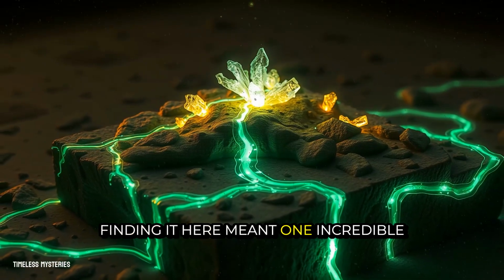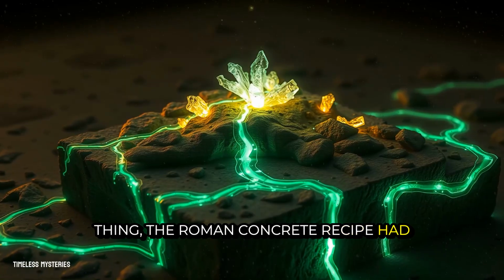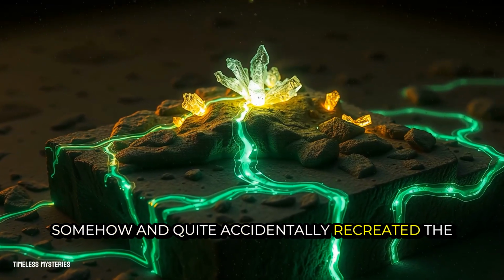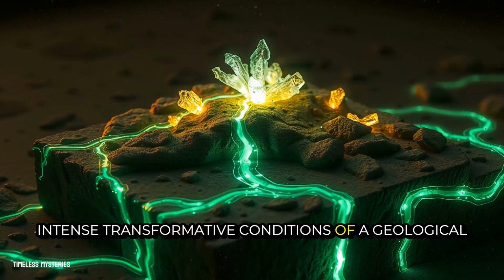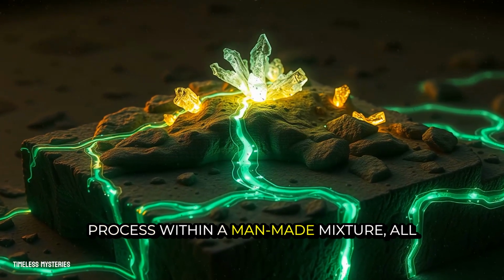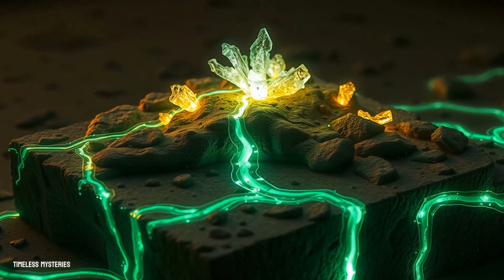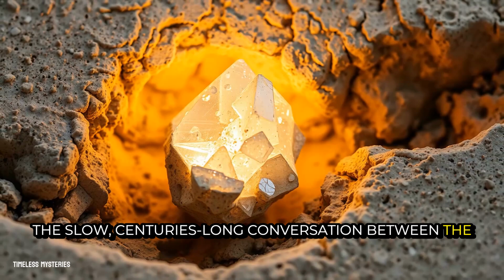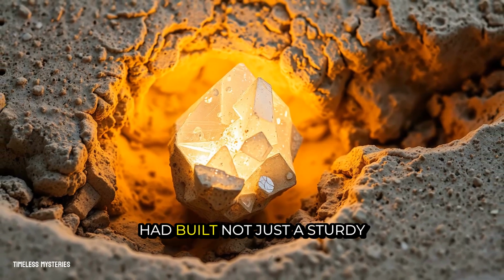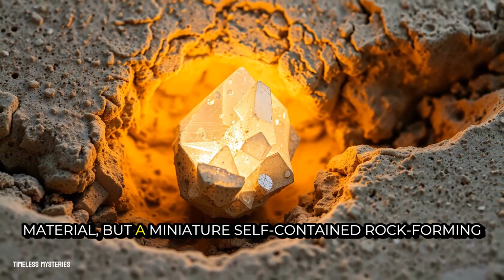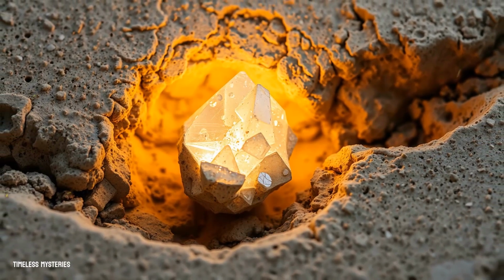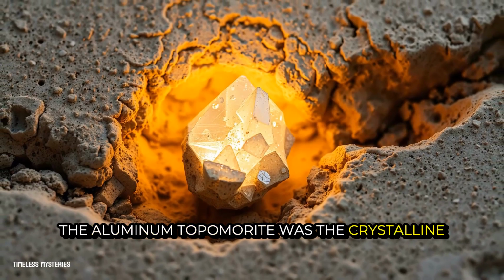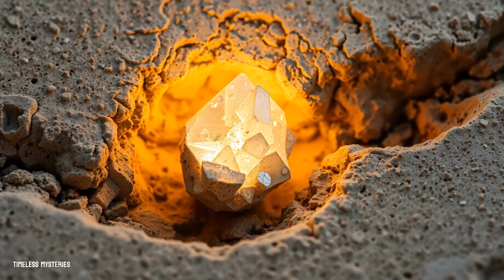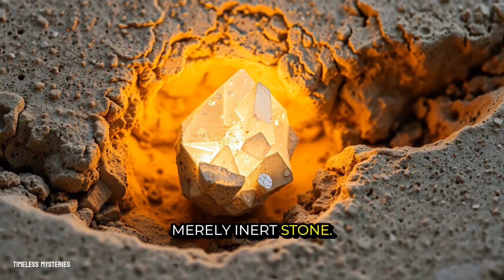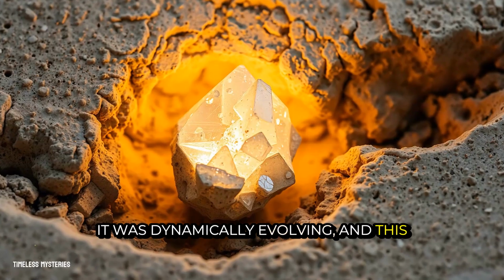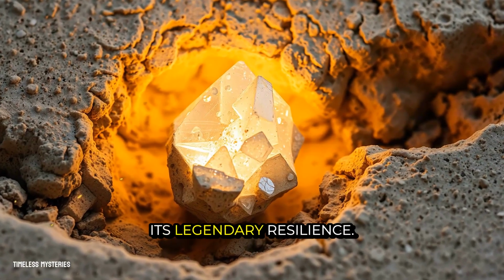Finding it here meant one incredible thing. The Roman concrete recipe had somehow, and quite accidentally, recreated the intense, transformative conditions of a geological process within a man-made mixture, all at room temperature. The slow, centuries-long conversation between the lime, the ash, and the seawater had built not just a sturdy material, but a miniature, self-contained rock-forming environment. The aluminous Tobermorite was the crystalline signature of that environment, the ultimate proof that this concrete was not merely inert stone. It was dynamically evolving, and this rare mineral held the key to its legendary resilience.